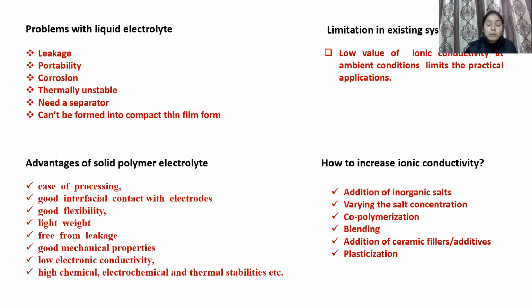Now, liquid electrolyte attracts many researchers due to its high ionic conductivity, but various problems such as leakage, portability, corrosion, and thermal instability limit the use of liquid electrolyte. The best alternative to liquid electrolyte is solid polymer electrolyte because of its advantages, such as ease of processing, good interfacial contact with electrodes, good flexibility, light weight, freedom from leakage, good mechanical properties, low electronic conductivity, and so on.